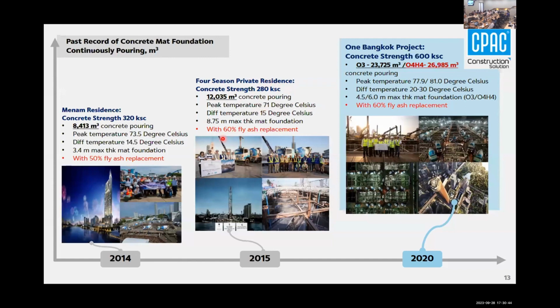But we use fly ash around 60% to replace the cementitious material. And the interesting thing for this project is the thickness is quite high, 8.75 meters. This is the highest thickness of mat foundation that we have ever produced. But it's not a big area, just in the core of the foundation.